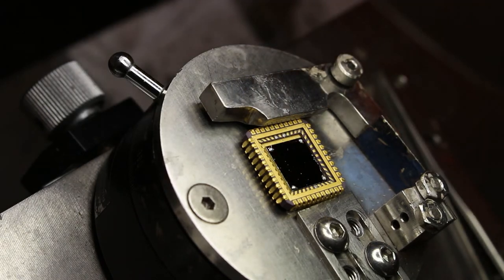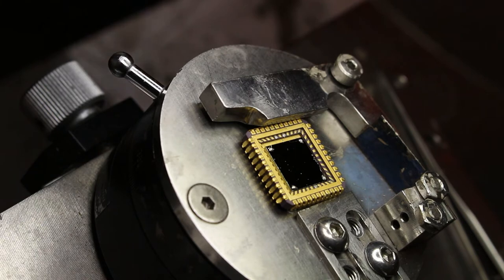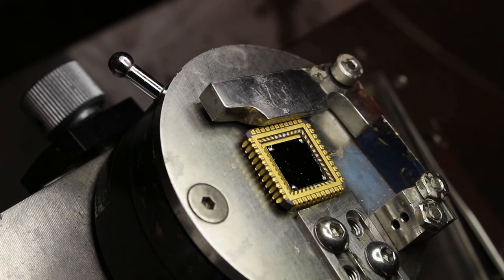You kind of have to play a balancing act between letting the silver paint get too dry and tacky and too liquidy. Because you don't want it to run and spread all over, but you also don't want it to stick to the wire and pull the wire away with you. So that kind of takes some luck and timing, and that depends on how old the silver paint is. A fresh bottle, you have the longest time to deal with. The widest window. Once you start using thinner in the silver paint, it doesn't seem to work as well. It just dries really fast. So make sure you're using a fresh bottle, and you shake it really, really well. And then when you're done, seal the bottle up very well with tape and make sure it doesn't dry out.